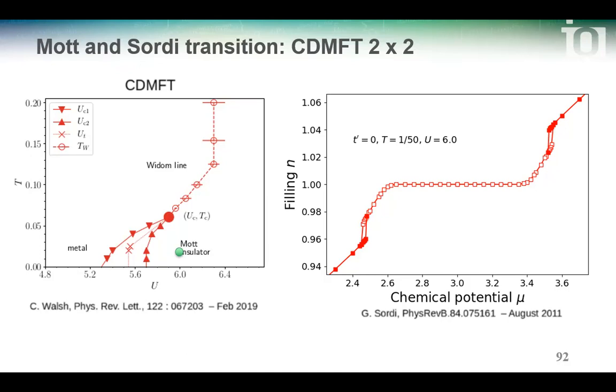If you talk about a quantum critical point, you mean that this point goes all the way to 0 temperature. In our case, it goes to very, very low temperature, but it's not 0 temperature. At 0 temperature, at least as far as we can extrapolate, this first order transition here or this one here still remains exactly first order.